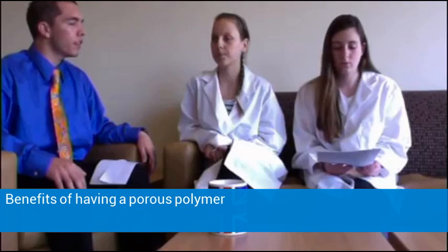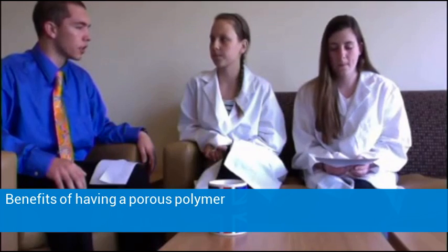The solvent that is added to the polymer is removed after the cast solution is cooled through solvent extraction, leaving behind a microporous structure of desired characteristics. And this actually lowers the energy of the polymer, and the polymer-rich portion resolidifies while the polymer lean portion turns into pores. What are the benefits to having a porous polymer?